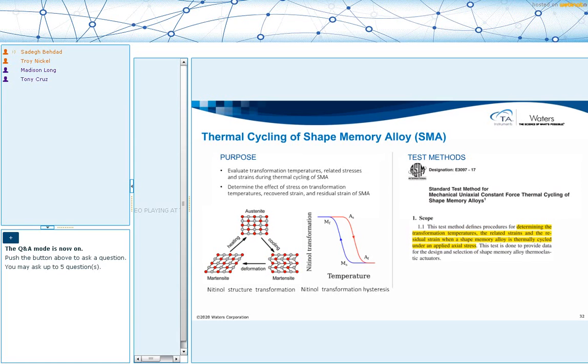And here we are studying the effect of thermal cycling on shape memory alloys. So basically, in a shape memory alloy, you have two phases. You have a high temperature phase, or austenite, which has a simple cubic crystal structure, and you have a low temperature phase, or martensite, that has a monoclinic, more complex crystal structure. And the solid state phase transformation is reversible, and it is very close to room temperature, and you can engineer that to happen at various temperatures by changing the dopants that you add to your nickel titanium or changing the proportions of these components in the alloy.